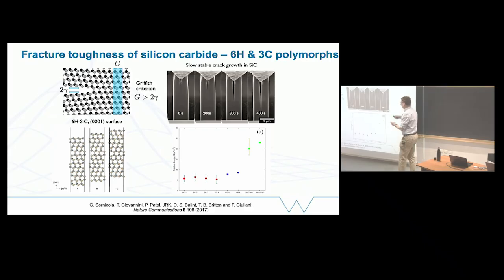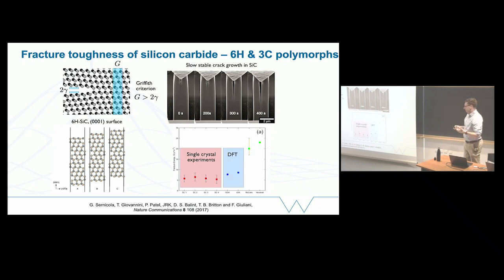And if you look at the load that they had to apply, you have to do some calculations at the continuum scale to work out what that load is. And you compare the single crystal experiments with the direct density functional theory calculations, you get reasonably good agreement within 10% or so, in comparison to previous experiments which weren't done so carefully or weren't so well aligned. So if we're talking about thermodynamics, then DFT is fantastic. We can compute quantities, we can make predictions.